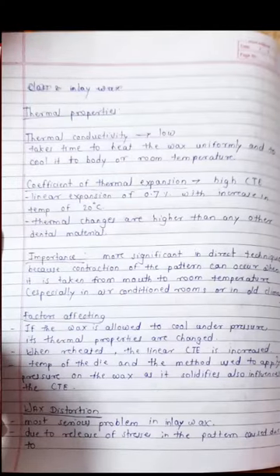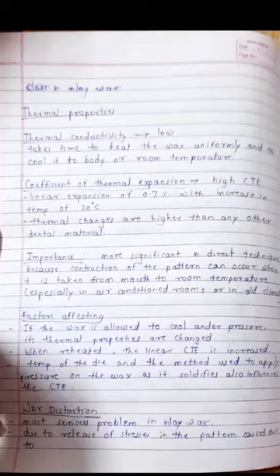Regarding thermal properties: thermal conductivity is very low, so it takes time to heat the wax uniformly and to cool it to body or room temperature. Inlay waxes have the highest coefficient of thermal expansion. Factors affecting thermal expansion include: if the wax is allowed to cool under pressure, its thermal properties change; also the temperature of the die and the method used to apply pressure on the wax as it solidifies influences the coefficient of thermal expansion.